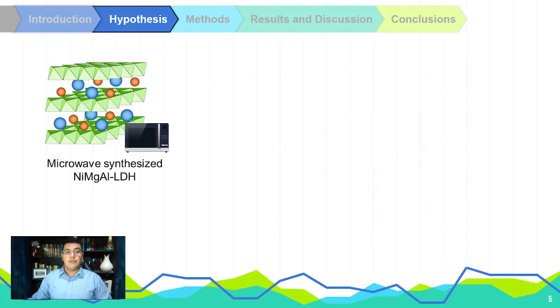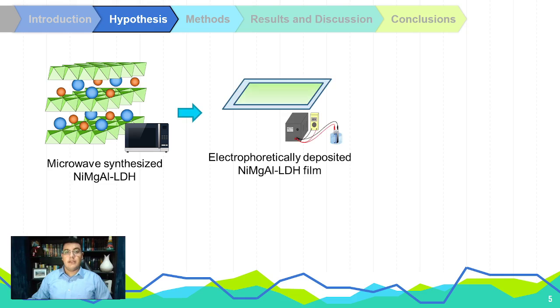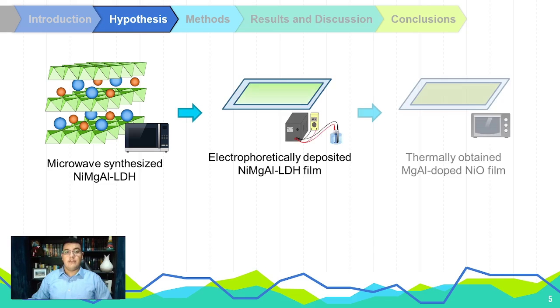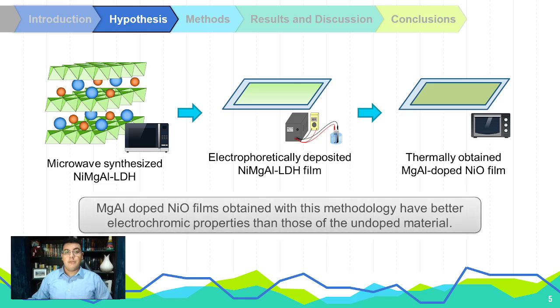This is why we propose a route where we synthesize a nickel, magnesium and aluminum LDH through a microwave-assisted process, then we carry out an electrophoretic deposition and thermally treat the obtained films. Our hypothesis is that the magnesium-aluminum doped nickel oxide films obtained through this process will have better electrochromic properties than those of the undoped material.